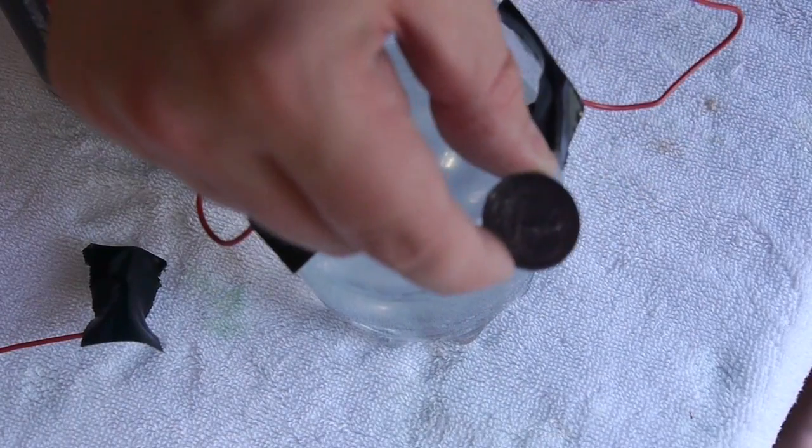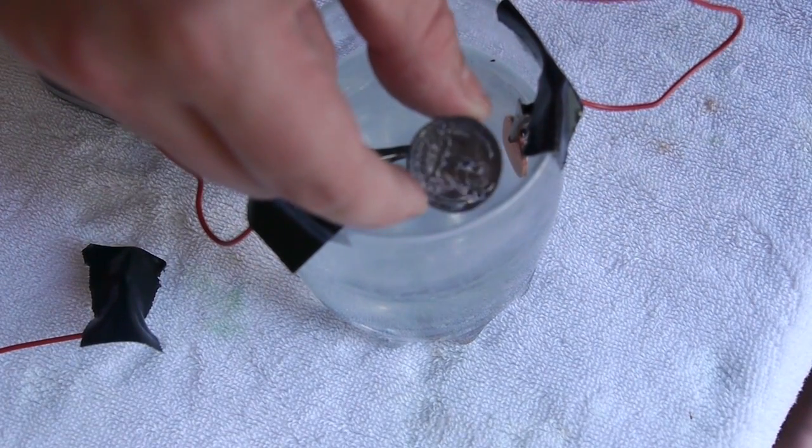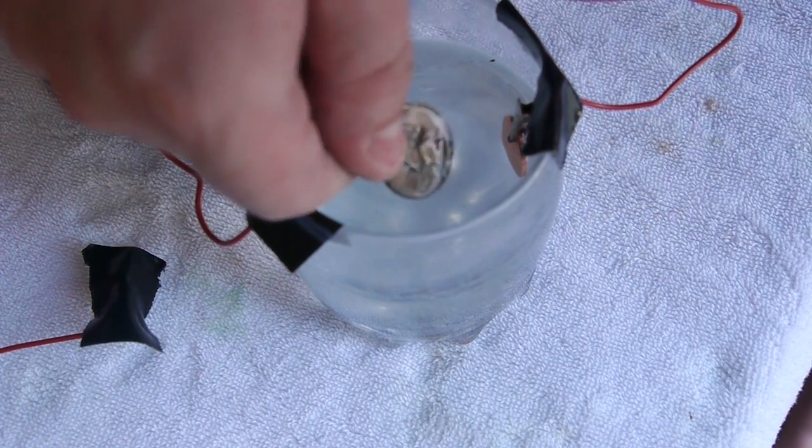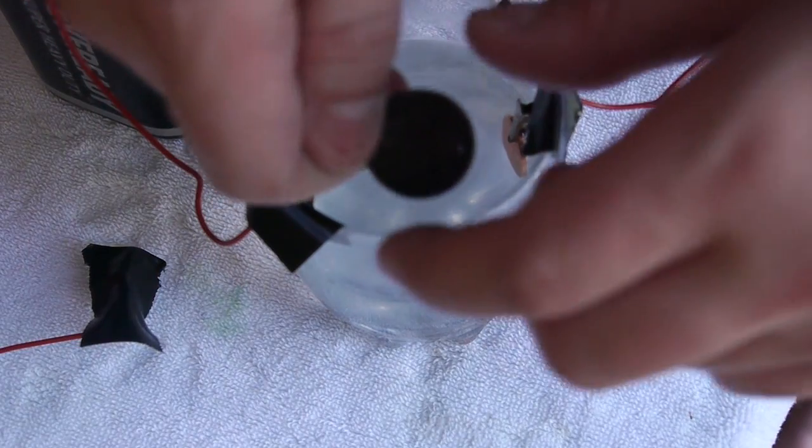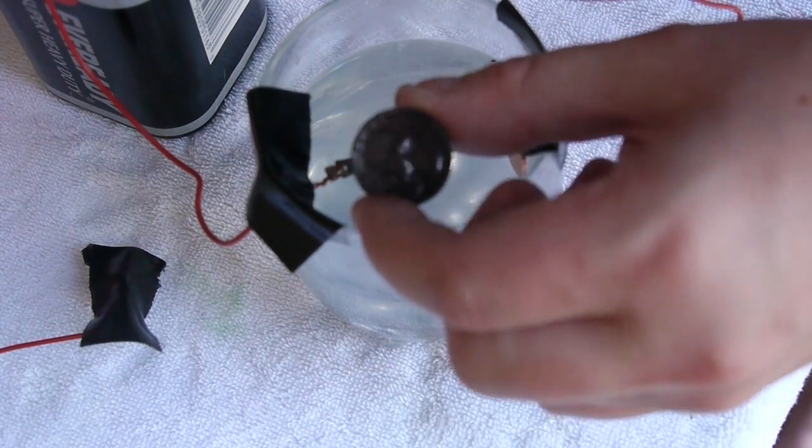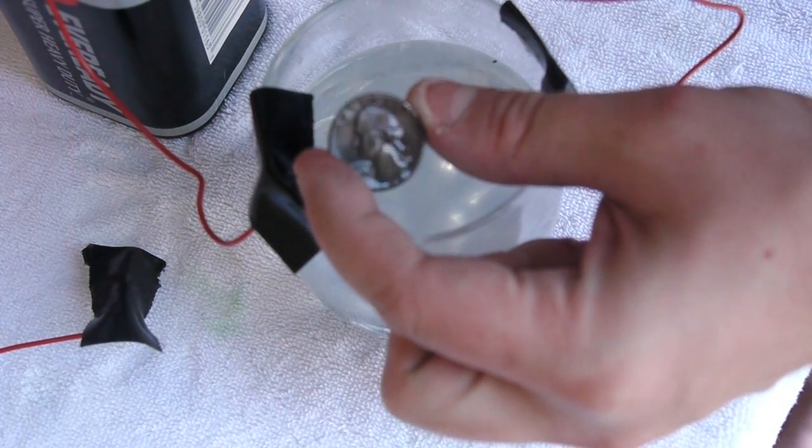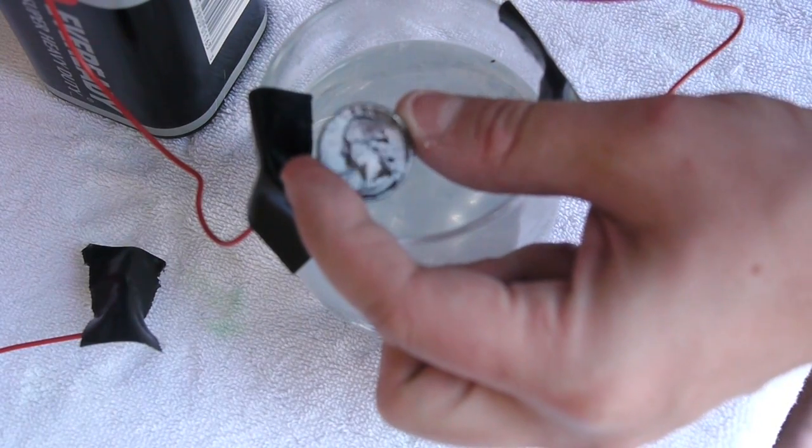After keeping the quarter hooked up for about 10 extra minutes on 6 volts, you'll notice that a black sheen appears around the corner. This is unfortunate, but you can alleviate it by using a smaller voltage on your battery. Try just a standard 1.5 volt battery. It is going to take longer, but keep your eyes on it and you shouldn't have any problems.